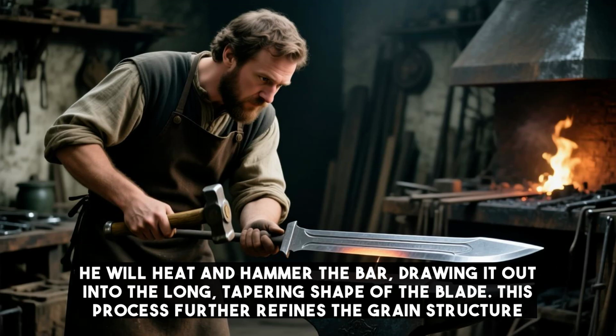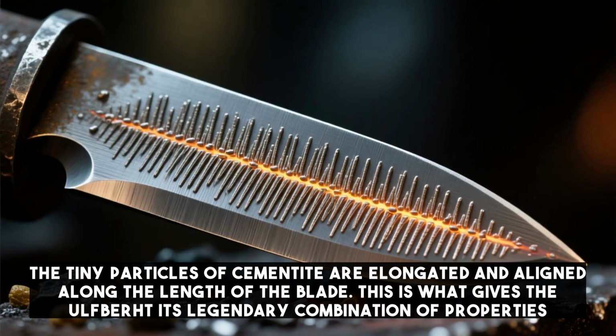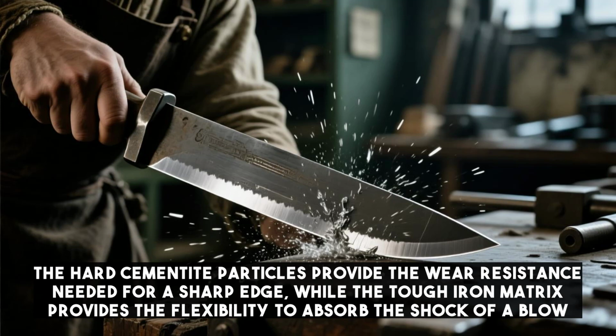He will heat and hammer the bar, drawing it out into the long, tapering shape of the blade. This process further refines the grain structure. The tiny particles of cementite are elongated and aligned along the length of the blade. This is what gives the Ulfberht its legendary combination of properties. The hard cementite particles provide the wear resistance needed for a sharp edge, while the tough iron matrix provides the flexibility to absorb the shock of a blow.